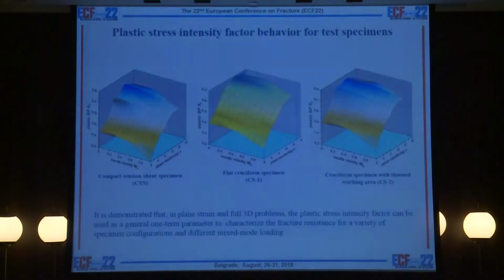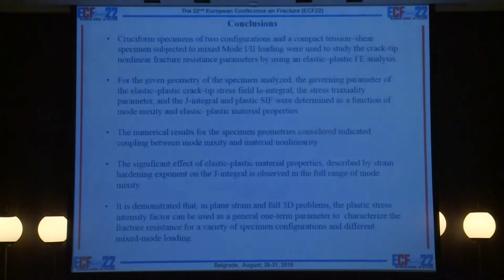In the next figure, you can see the plastic stress intensity factor distributions as a function of both the mode mixity parameter and elastic plastic material properties, which are described by the strain hardening exponent. And these results demonstrate that in plane strain and full three-dimensional problems, the plastic stress intensity factor can be used as a general one-term parameter to characterize the fracture resistance for a variety of specimen geometries and different mixed mode loading conditions. And now I have to conclude.